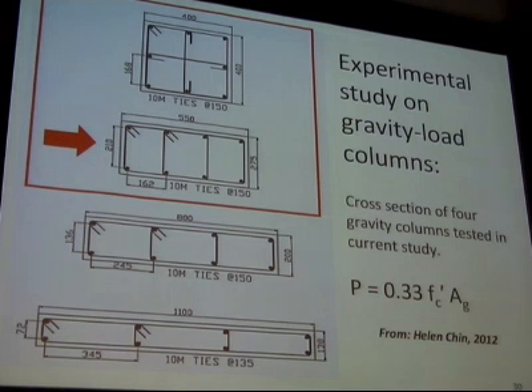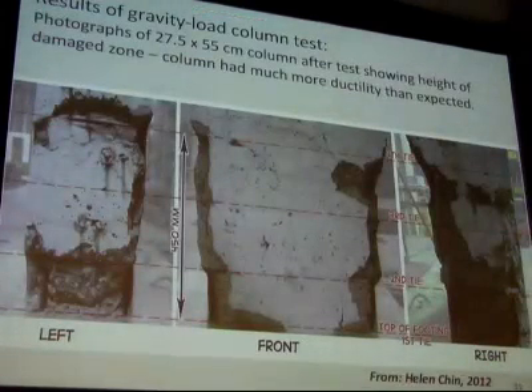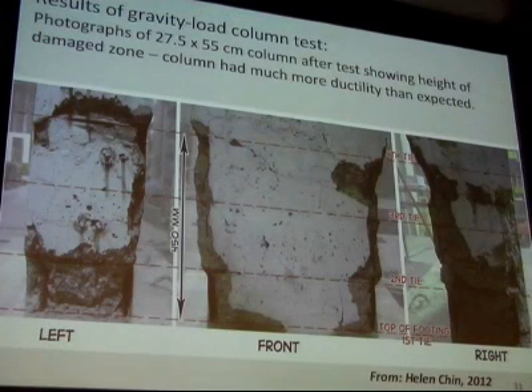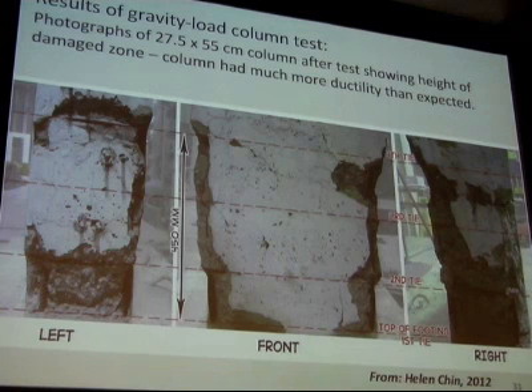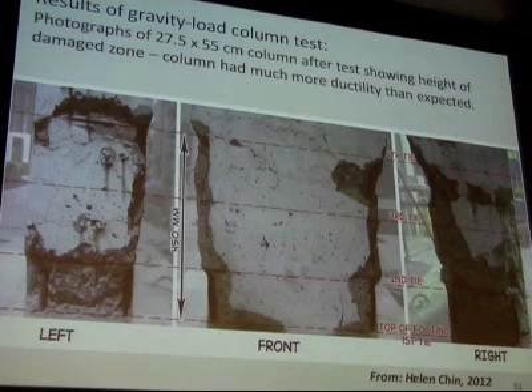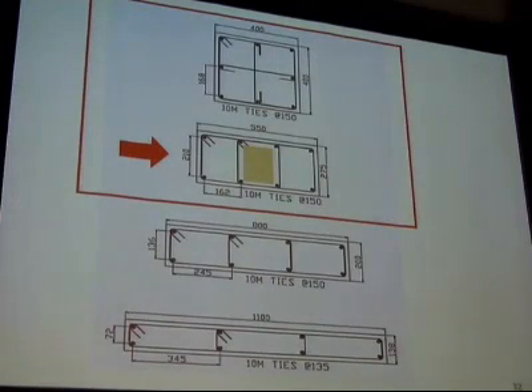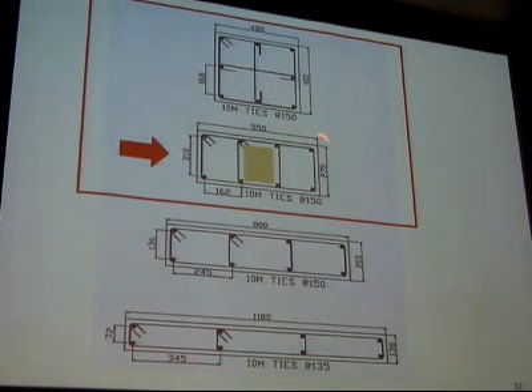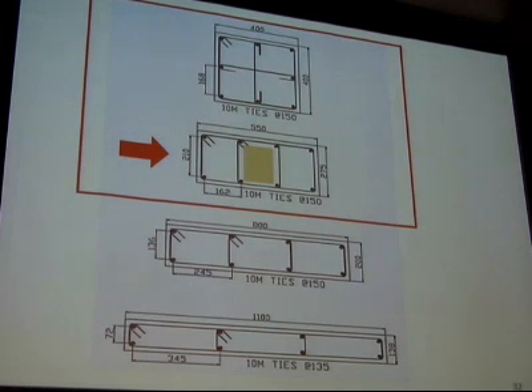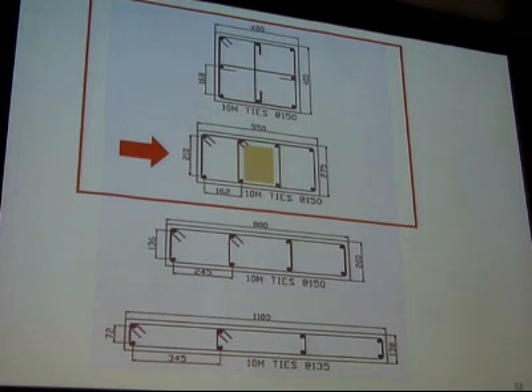Okay, if we focus in on this column, and we look at what our predicted displacement capacity was, it was much greater from the experiment. Essentially, we couldn't break it. Okay, we crushed all the concrete on the outsides, but it still carried the load, and it had a heavy load, 33% of f'c Ag. And the reason why it works so well is because in this middle zone here, you can crush all the concrete here and here, but this middle zone, which has some nominal ties around it, continues to carry the gravity load. So we were really surprised at how good some of these gravity columns can be. And that's, of course, great news.